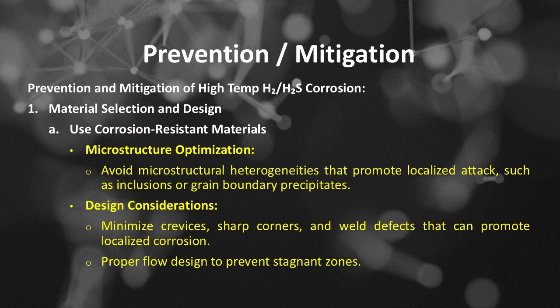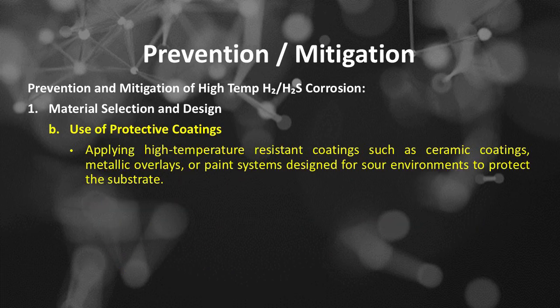The second is microstructure optimization: avoid microstructural heterogeneities that promote localized attack, such as inclusions or grain boundary precipitates. The third is design considerations: minimize crevices, sharp corners, and weld defects that can promote localized corrosion. Proper flow design to prevent stagnant zones. Number B of the material selection and design is use of protective coatings. Applying high-temperature resistant coatings such as ceramic coatings, metallic overlays, or paint systems designed for sour environments to protect the